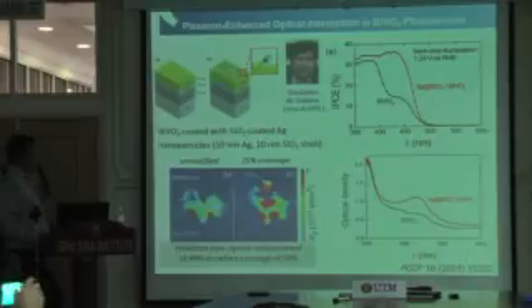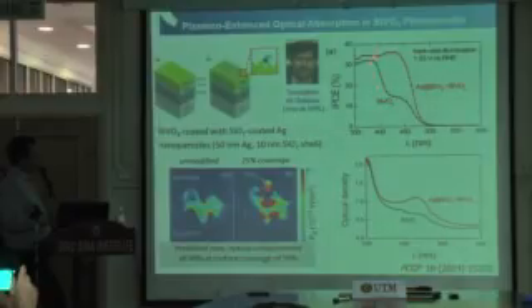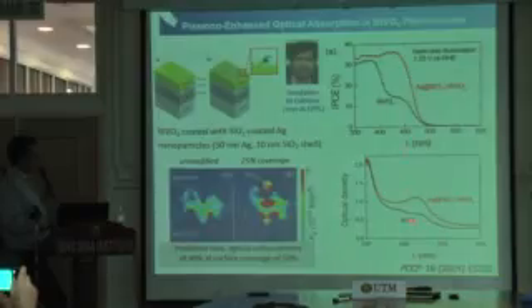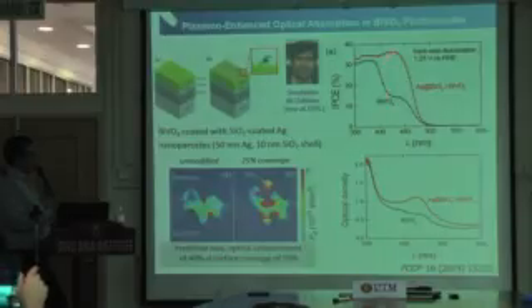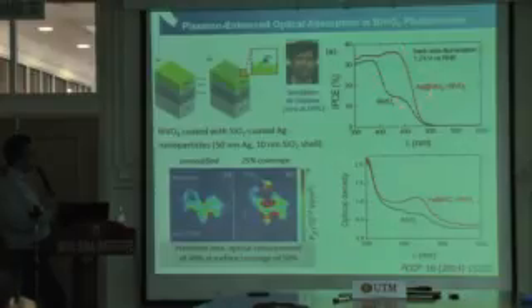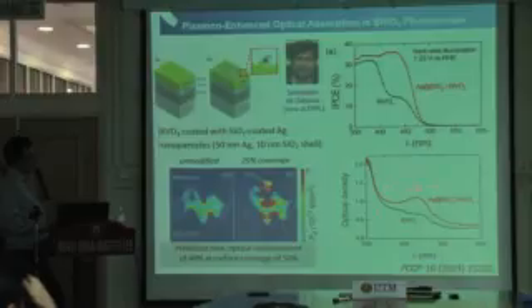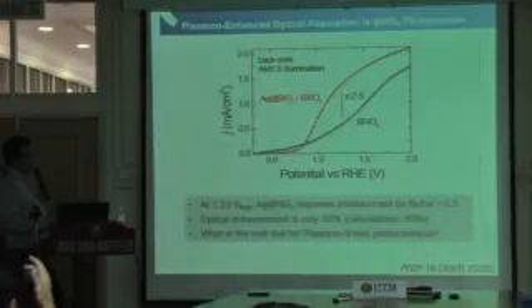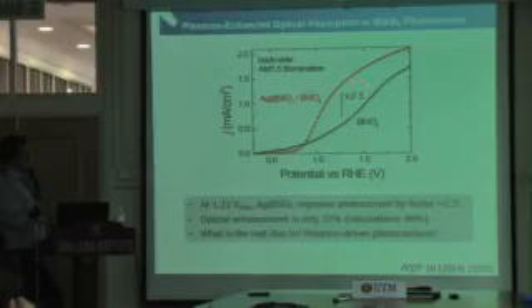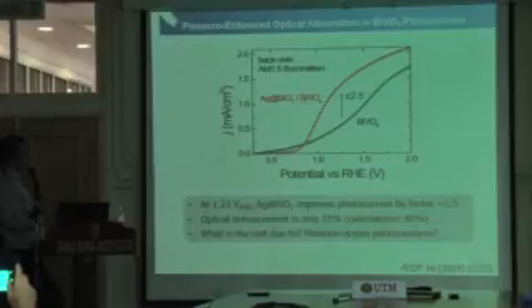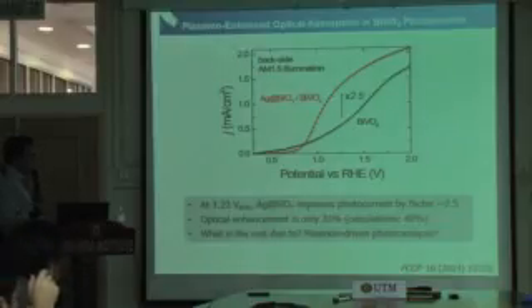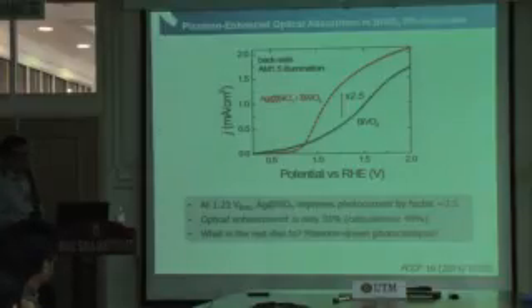Then we did the experiment, we prepared this sample, and indeed we see an enhancement of the quantum efficiency and also the absorption, in agreement with what's predicted in the calculation. We got this enhancement of quantum efficiency in the wavelength range where silver silica contributes, as well as the absorption. And if we look at the AM1.5 illumination, we also see a factor of 2.5 enhancement of photocurrent after we put the silica-coated silver nanoparticles. The enhancement factor is actually 2.5, whereas if you remember from the previous slide, I said maximum 40%.